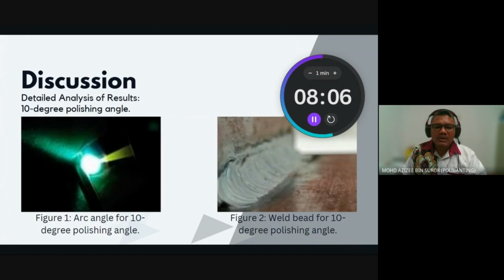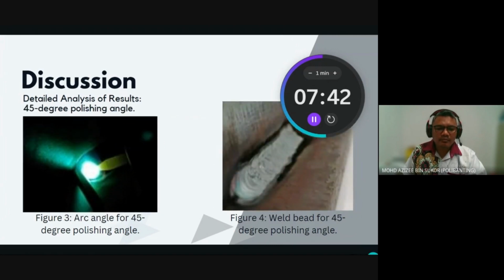For the 10-degree polishing angle, it produced a larger arc angle and significant molten pool expansion, yielding a wider weld bead, as depicted in figure 1 and figure 2. Contrary to modest expectation, this angle demonstrates benefit for applications requiring wider weld. For the 45-degree polishing angle, it created a moderately sized arc and molten pool, as shown in figures 3 and 4. Metal accumulated more than it spread, resulting in a narrower but taller weld bead. This suggests an advantage for applications that require thicker weld.